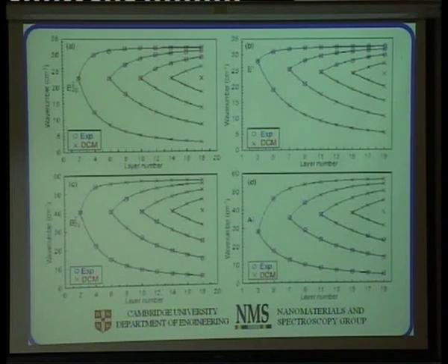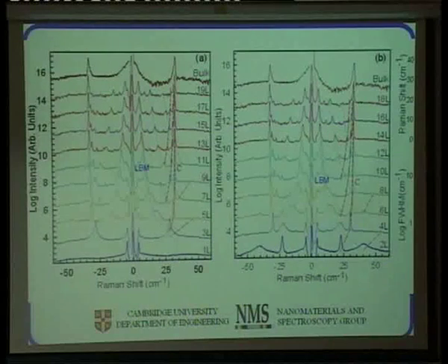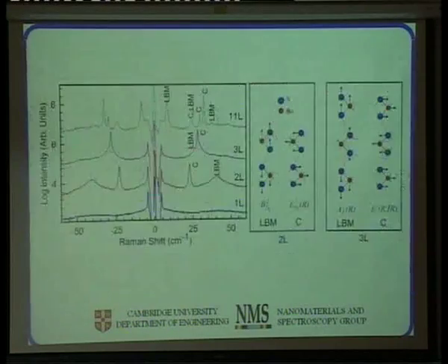So now all the story is sort of taken on, and the reason why it has become very simple to do the measurement is that a company called Bragg-Grate has developed a set of filters that can be retrofitted to the most modern Raman spectrometer systems, and so, since about 1 year, you can do these measurements with high intensity and you don't need to use an old triple spectrometer in subtractive mode and so on and so forth.